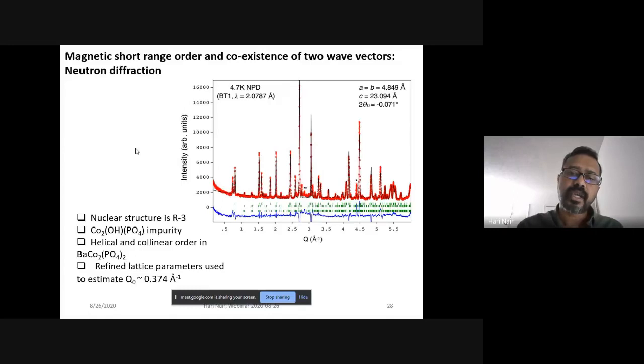With this data, we actually confirmed all the results that we saw in the previous X-ray diffraction analysis. It means that it is honeycomb, it has R3 structure, A and B are 4 angstroms, and the C axis, which is perpendicular to the honeycomb layers, is 23. That translates to about 7 or 8 angstrom separation between the cobalt layers, which makes it 2-dimensional.